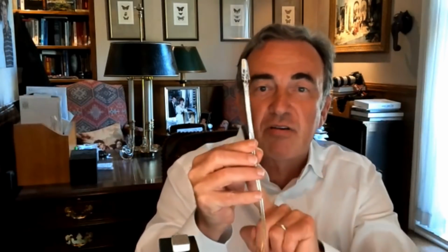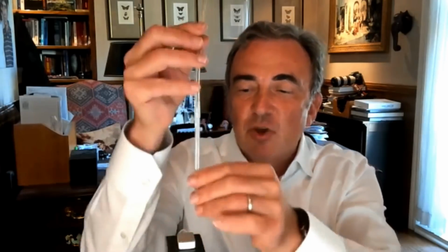Now, the beauty about our process is that we attach the nanowires to the graphite directly into the graphene layer at the surface of the graphite particles. And that attachment is both mechanically and electrically permanent. And it doesn't use any polymers. So why is that so important? Because in order to store lithium into my nanowire, I need not only the lithium ion to come from the electrolyte, but for each lithium ion, I need an electron to come in. And the graphite is essentially the supplier of the electrons. And the attachment point is the plug.